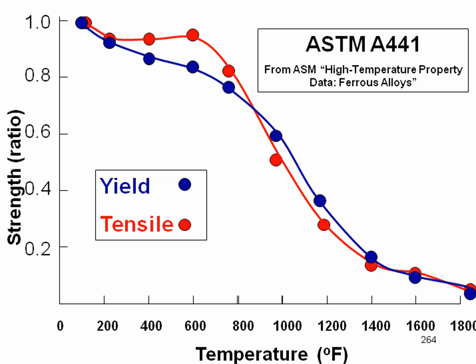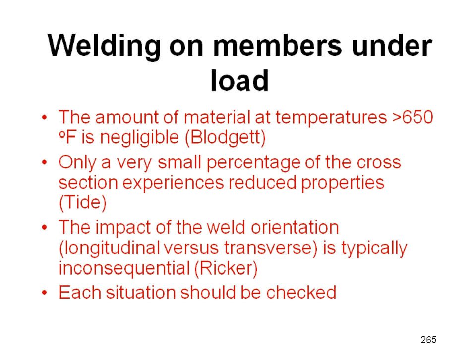Now, here's what some other authors have said on the issue of welding under load. My mentor, Omer Blodgett, says the amount of material at temperatures greater than 650 F is negligible. Dr. Tide of Wiss, Janney, Elstner, only a very small percentage of the cross-section experiences reduced properties. The late Dave Ricker, the impact of the weld orientation, whether it's longitudinal versus transverse, is typically inconsequential. And I say you need to check every situation. But these are some general trends that might be helpful to you.